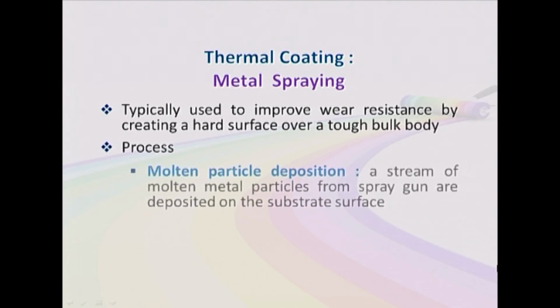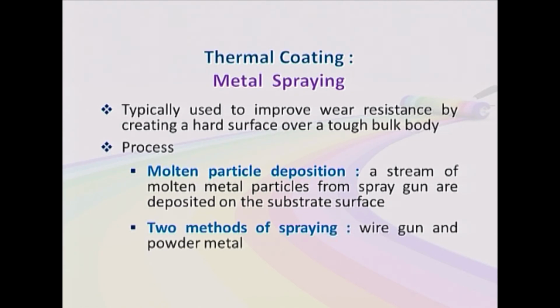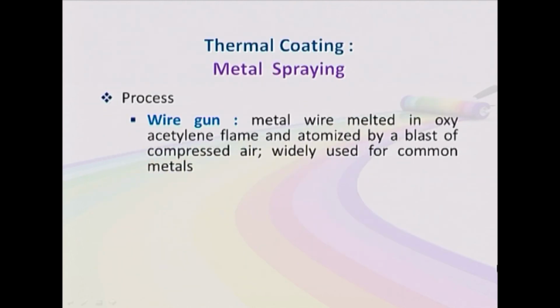Next type of thermal coating is by metal spraying method. This is typically used to improve wear resistance by creating a hard surface over a tough bulk body. In this process, molten particles are deposited. A stream of molten metal particles from a spray gun is deposited on the surface of the substrate. We can deposit the stream of particles by two methods: wire gun and powder method. In the wire gun method, metal wire is melted in an oxyacetylene flame, and then it is atomized by a blast of compressed air. This method is widely used for common metals.